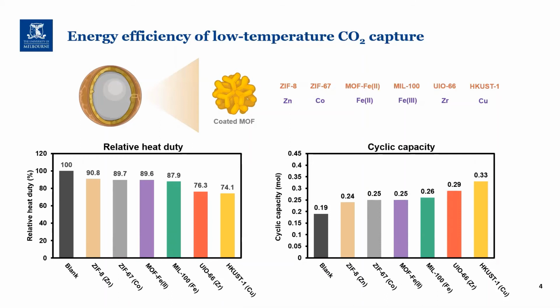The experimental results confirmed that all prepared nanocatalysts with different coatings can facilitate carbon dioxide desorption and reduce the amount of required energy. Interestingly, zirconium and copper-based nanocatalysts displayed a distinguished performance during the regeneration of amine solution, resulting in 24 to 26% energy reduction.